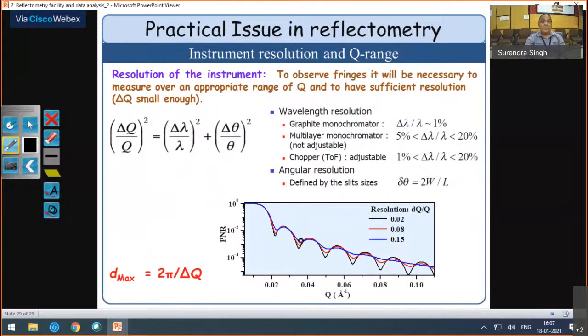This is also important because it decides what should be the maximum single layer thickness we can study from our instrument, which is nothing but 2 pi by delta q, where delta q is the resolution of the instrument. So it decides the maximum thickness we can study. If the sample thickness is greater than this maximum, it will look like just a substrate.